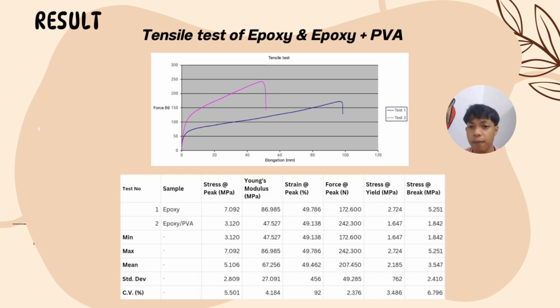If we look at the graph at the bottom, we can clearly see the difference. The blue curve represents epoxy and it breaks at a lower elongation. The purple curve, which is epoxy plus PVA, extends much further and shows more flexibility. So the epoxy is suitable for applications that need high strength and stiffness, but it is more brittle. Epoxy mixed with PVA is more elastic and flexible, which makes it better for non-structural or packaging applications.